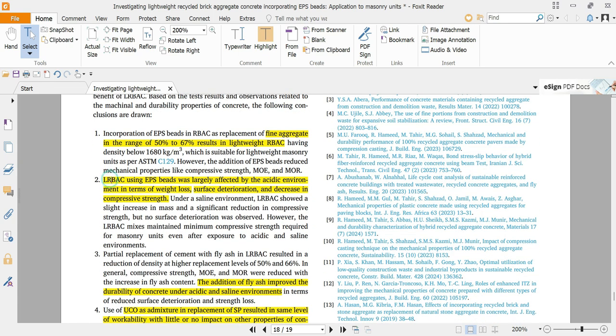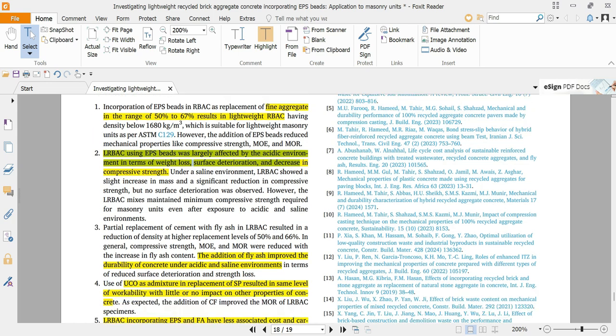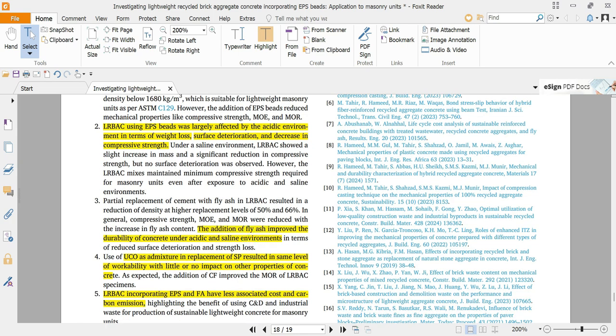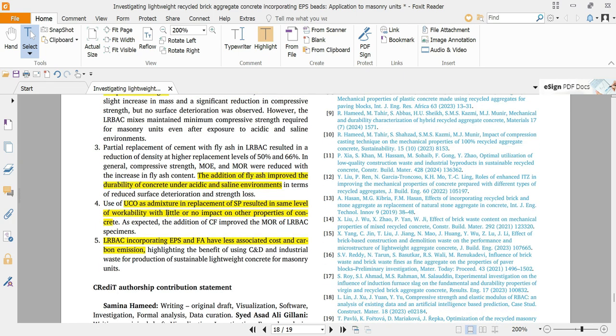Moreover, if we see the durability, the lightweight recycled brick aggregate concrete using EPS beads was largely affected by acidic environment. So its durability was less in acidic environment. But we can improve the durability in acidic environment by incorporating fly ash. So when we use fly ash as a replacement of cement, its durability was significantly improved, both in acidic as well as saline environment. Moreover, the used cooking oil improved the workability, meaning it effectively substitutes the conventional or the commercial admixtures without affecting the strength as well as durability of the concrete.